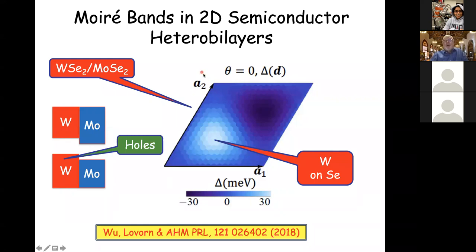The reason that's important is because with this huge lattice constant, you can change the number of electrons per effective atom just using electrical gates. Typically with electrical gates, you can change the number of electrons per atom in a two-dimensional crystal by around 10 to the 13 per square centimeter. Other techniques allow you to go somewhat larger, but for Moiré superlattices, 10 to the 13 is plenty.